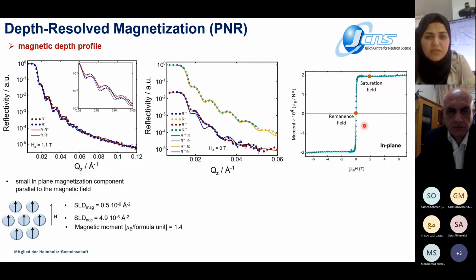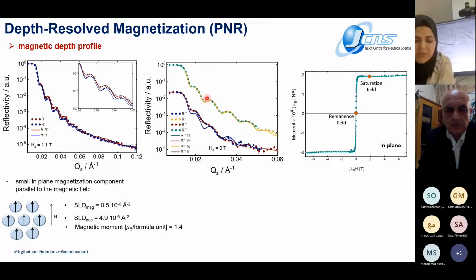At the second field, around 0 Tesla, we measured the full polarized neutron reflectometry, also in plane, and we can see here the upper curve is the spin flip curve, and we see that there is no splitting in the spin flip, which is an indication of complete randomness of the spins over the whole coherence volume, or of zero net magnetization. Also the non-spin flip shows no splitting, which also indicates that my sample goes to the demagnetized state at zero field, or at the remanence. The difference between spin flip and non-spin flip is due to the efficiency of the polarizer and the analyzer.